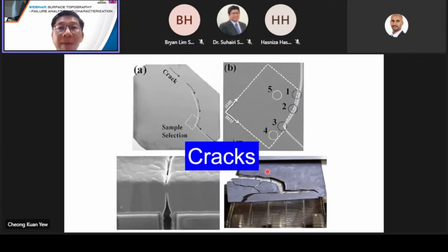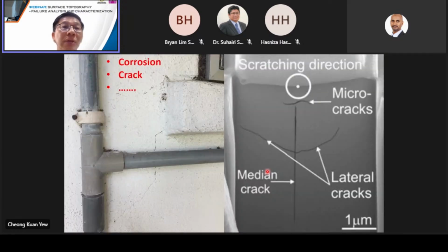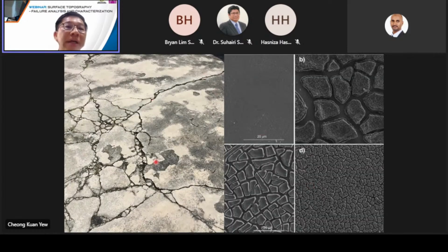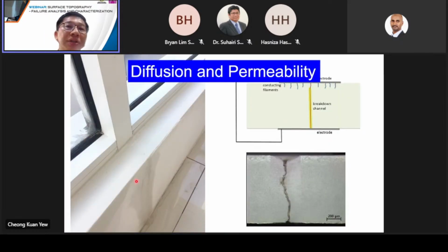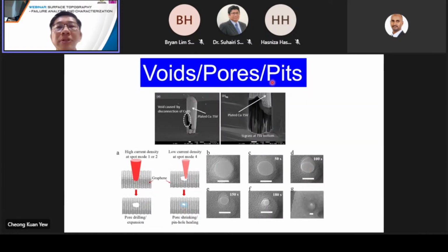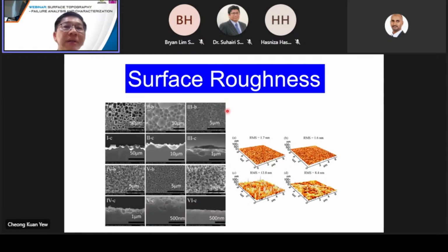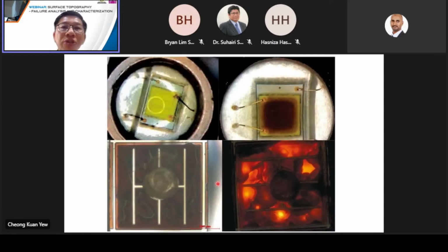Examples here: peeling off, delamination, cracks, right? Here I show you a crack on the wall. What is the difference between this crack on the wall and the crack inside your die? And you have cracks on the concrete floor, at a big scale, versus the crack of your thin film. And you have leakages due to diffusion and permeability. This issue also happens in semiconductors at a tiny scale. So: voids, pores, pits, roughness, discoloration, and so on.